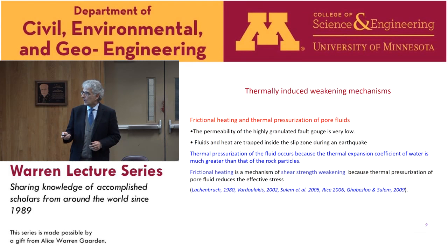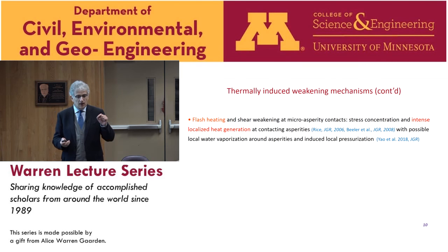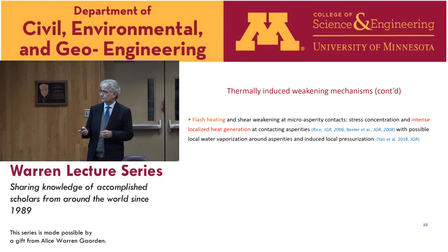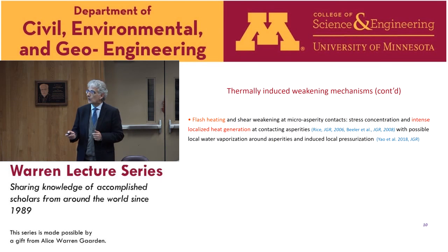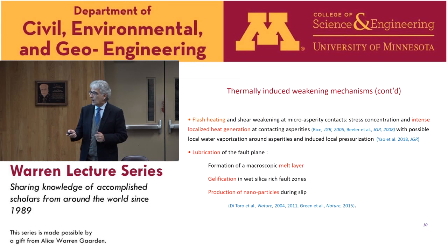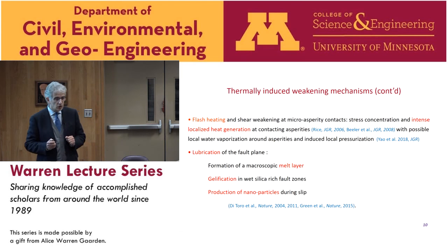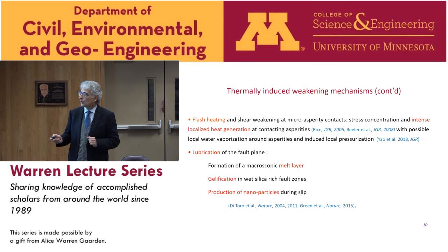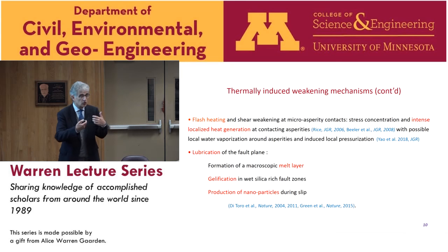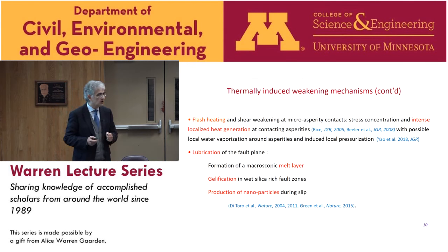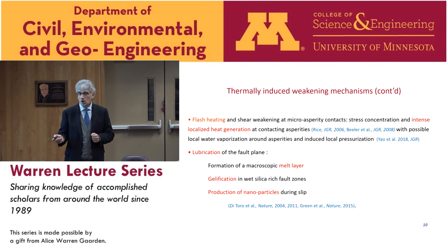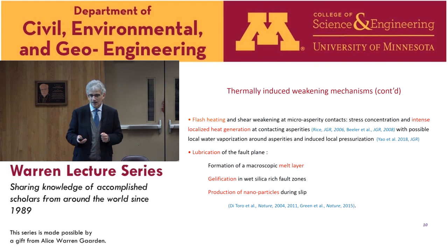Some other thermally induced mechanisms can affect directly the friction coefficient, and among them the flash heating, which is occurring at microasperity contact, and due to stress concentration, intense heat generation, and for rather shallow conditions, we can even have local water vaporization and induce local pressurization. Other mechanisms of reduction of the friction resistance are linked to the lubrication of the fault plane, either by the formation of a macroscopic melt layer, jellification of wet silica-rich fault zones, and also the production of very small particles, nanoparticles, due to the wear of the asperities, but also of tribochemical reactions. I will discuss this point a little later in the talk.